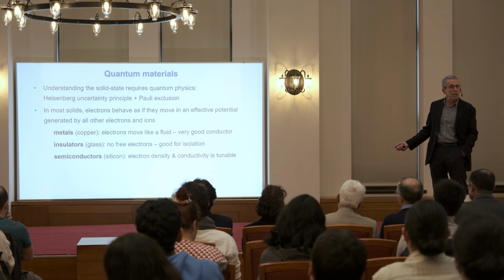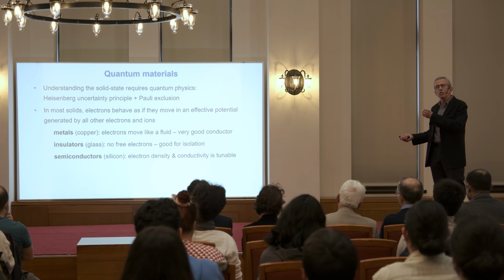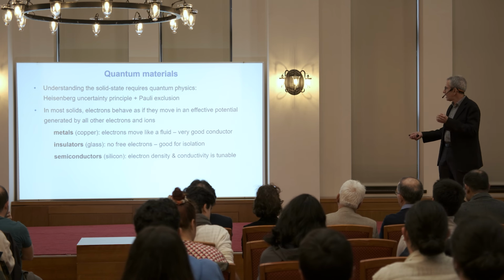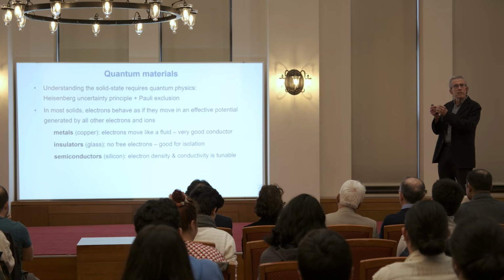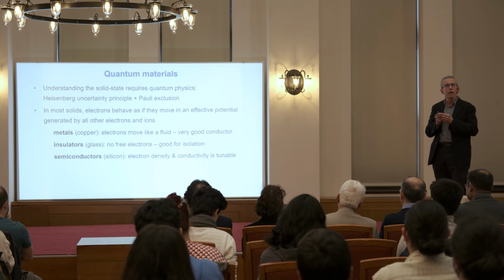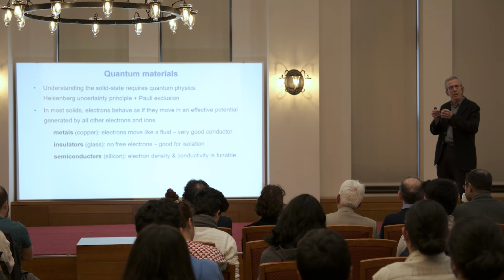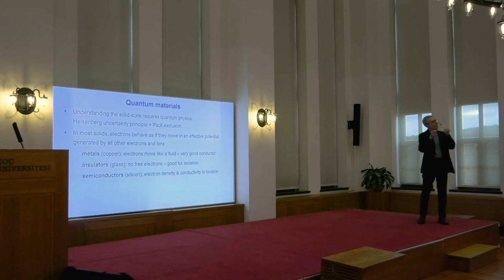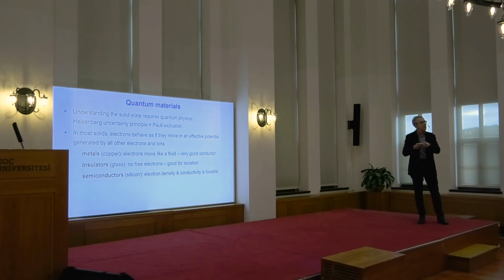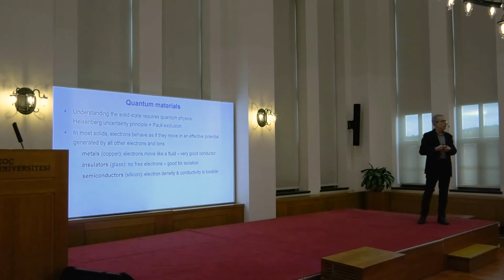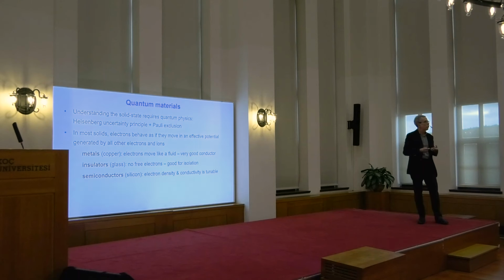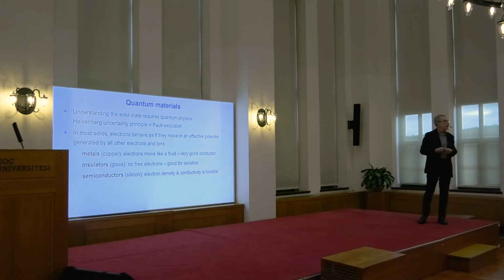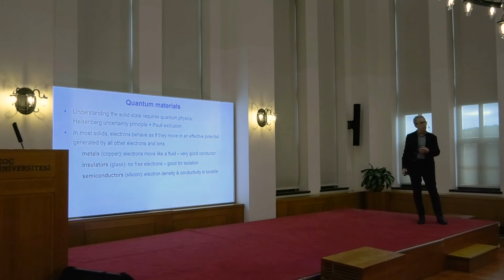And here, what makes them special is that we can actually tune the properties or the electron density such that, by using an applied voltage, we can turn the material into an insulator, and then by changing the voltage, it can become a reasonably good conductor. And this is an essential element of how, let's say, field effect transistors work.